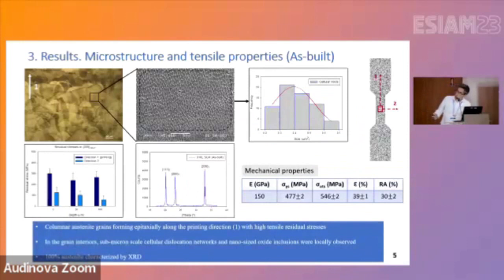Regarding the results, here we can see the microstructure after the SLM process. We can observe columnar austenite grains growing epitaxially along the printing direction 1. This is the position of the bed. And we have also measured the residual stresses in both directions, 1 and 2. We can observe the residual stresses are in the range of 300 megapascals in this direction. Here in the grain interior, we can observe cellular structures with this size distribution.